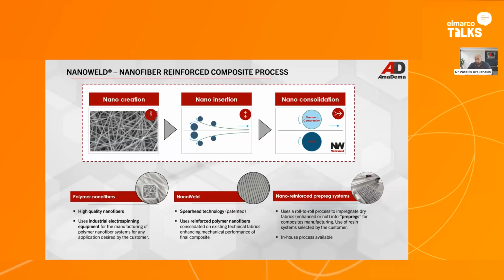So basically, out of this process, our products are of three main categories. Plain nanofibers, that can be enhanced with particles, or dry fabrics enhanced with nanofibers, like carbon fiber of different width. We can apply the nanofiber on any type of weaving, unidirectional, woven, twill, biaxial, and also different GSMs of fabrics, and eventually also the impregnation system. So an intermediate product that is already pre-impregnated with resin.